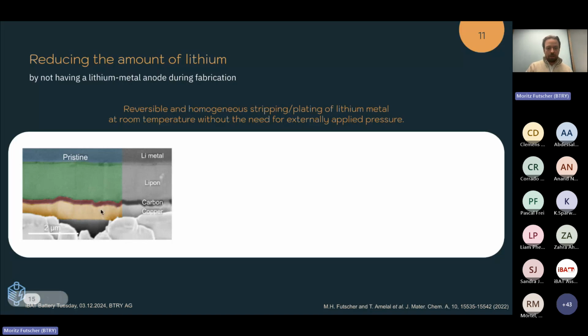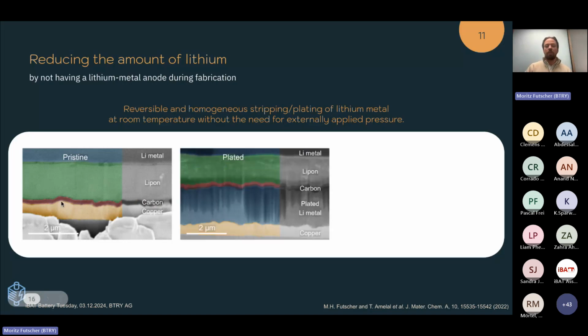So you see the copper on the bottom, and then there is a small interlayer, in this case carbon, and then the solid-state electrolyte LiPon. This now represents the anode side of the cell, where there would be no anode present, just a carbon interlayer. The work here was really focused on this interface and on developing a material which allows for stable plating and stripping of lithium metal. In this case, this was a carbon interlayer right here. And what we could show is that we can now very homogeneously plate this lithium metal. So what you see here in the middle graph is where, from the top, we apply the current and grow this lithium metal.